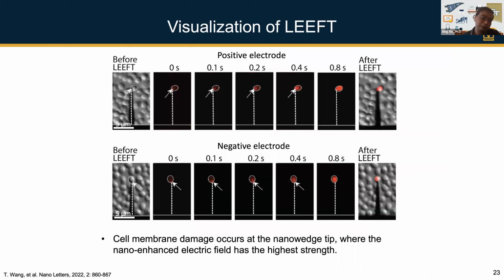So once we visualize it, we use this platform to do a lot of studies, right? So one of these is, for example, we zoom in. All right, so we're looking at the individual cell, individual nanowire. We notice that the diffusion of this dye into the cell really starts from one point. Like for example, this is 0 second, it's pretty dark inside. Starting from 0.1 second, 0.2, within 1 second, it becomes a completely red cell, red dot. And then you can see a diffusion of the dye from the point very close to the tip of the nano wedge. The similar phenomenon can also be observed for the negative electrode, right?